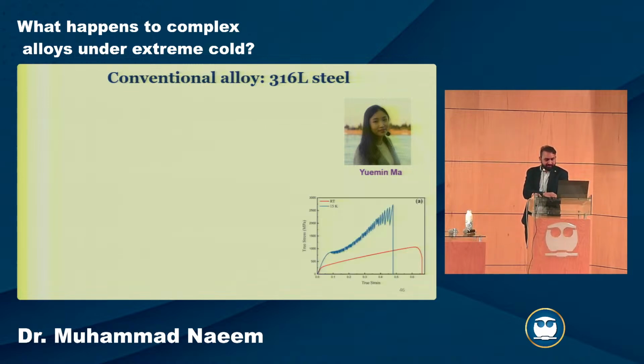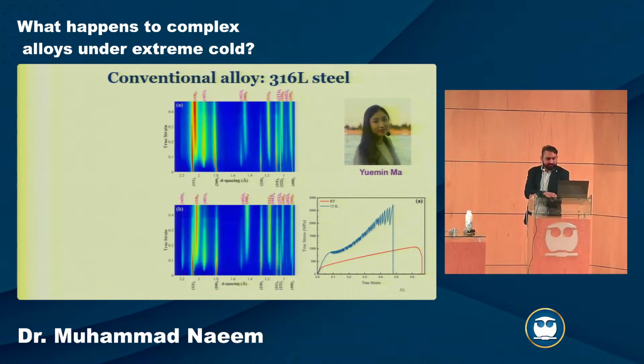If you look at the 316 steel, its testing curve, it does not become brittle at low temperature, it has significant ductility, but it does not increase. But if you look at its strain hardening, like how much it hardens, or work hardening, what we call, it's very significant compared to room temperature. So now you look at these diffraction patterns, this map, and these are along two directions, one is the loading direction, one is the transverse direction.